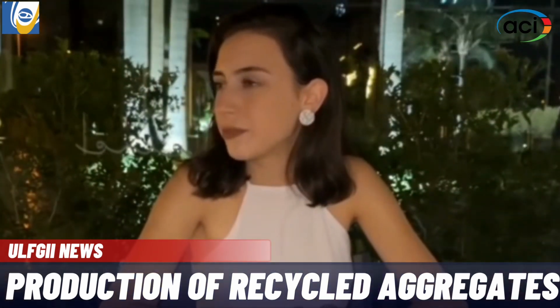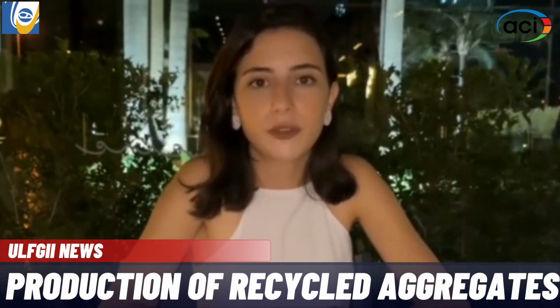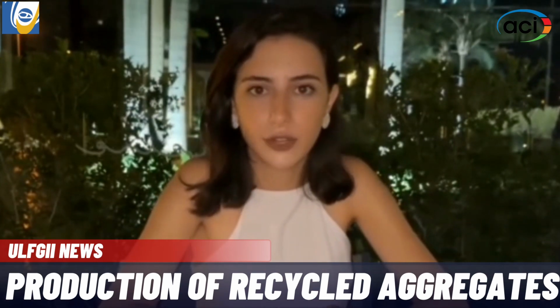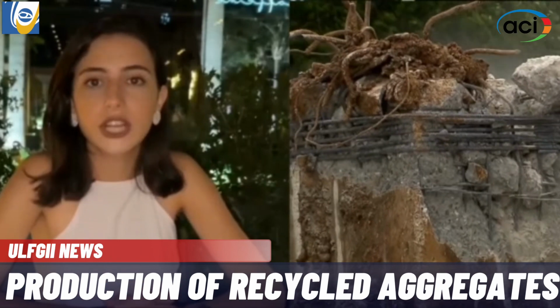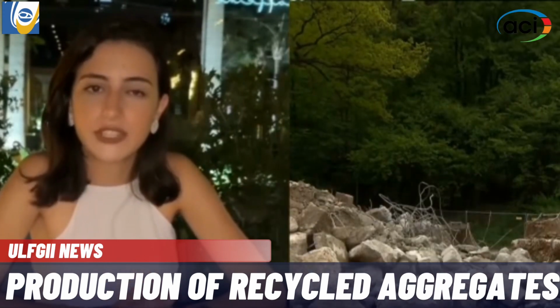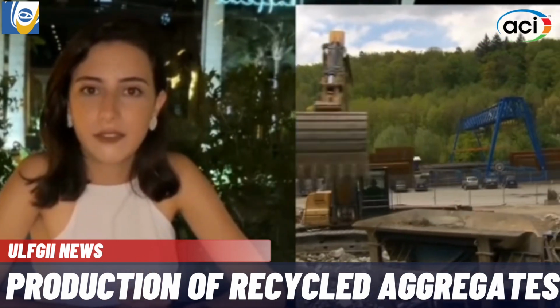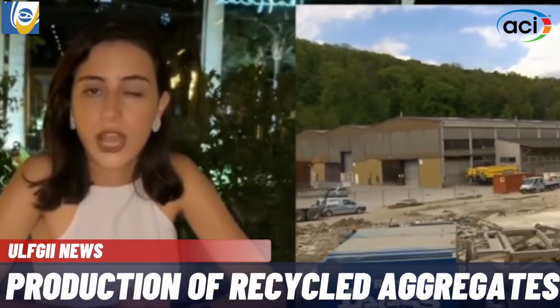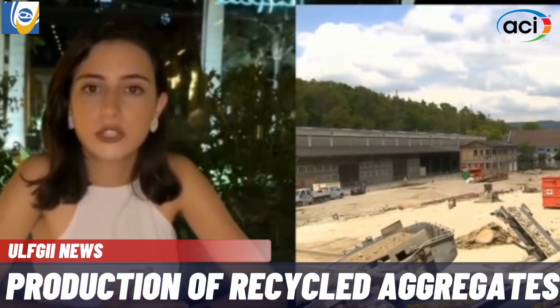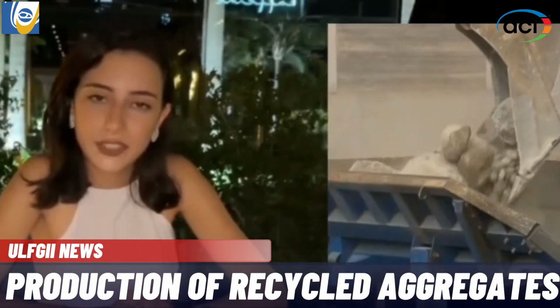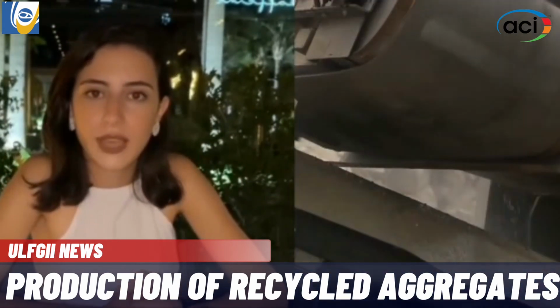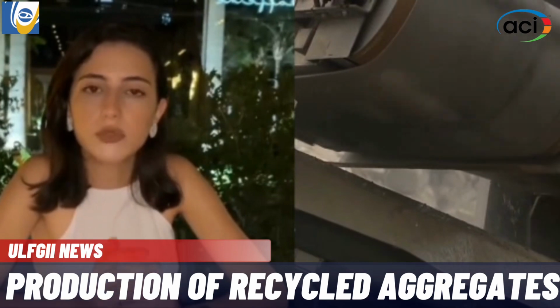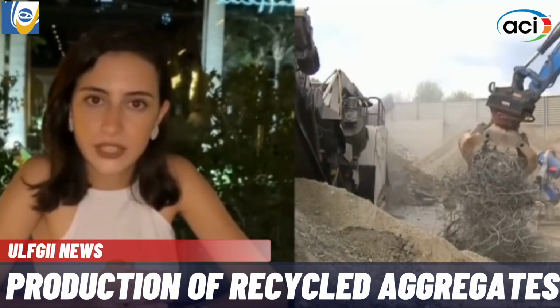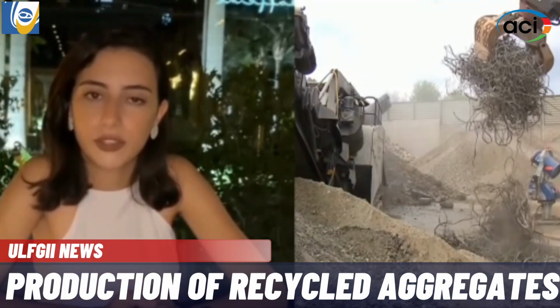Thank you, Edwin, for introducing me. As mentioned, the steps of production of recycled aggregates are as follows. First of all, a hydraulic chisel breaks up concrete and masonry on site. Second, an excavator dumps the material into a crusher. Then, the crusher processes the parts into materials with a particle size of up to 60 millimeters. After that, recyclers use magnets and water flotation to remove the metal, dirt, and other materials that may bother the recycling of concrete.